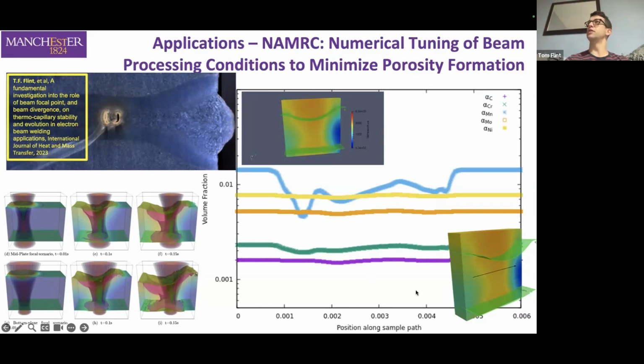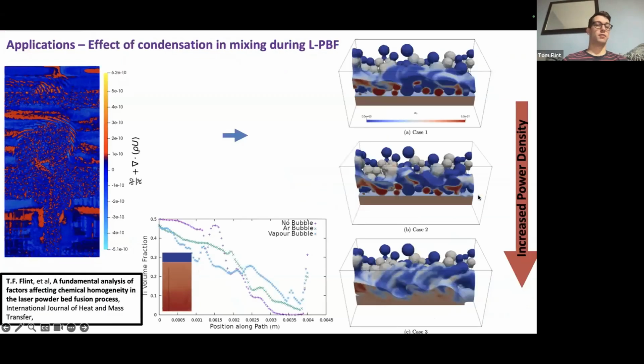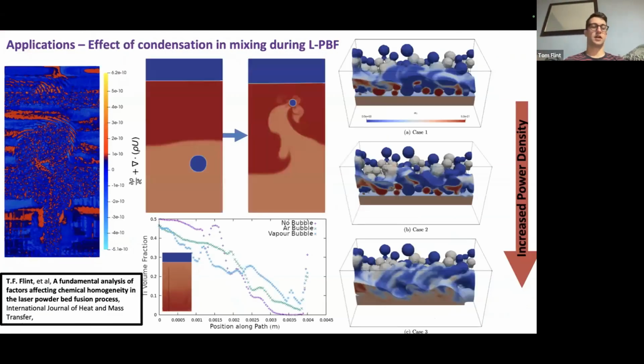And what's nice about our framework is that because it's a fully multi-component framework, we get predictions of the element evaporation losses for free. What happens in these materials is that the elements of the alloy that are more volatile evaporate preferentially. In an SA508 steel, it's a known phenomenon that you get manganese evaporating preferentially, and we just predict that for free. So we can predict effectively the different alloy that you'll get in your joint region. That's another really novel aspect of our work. And because the physics is universal, we can apply that to any system, basically.